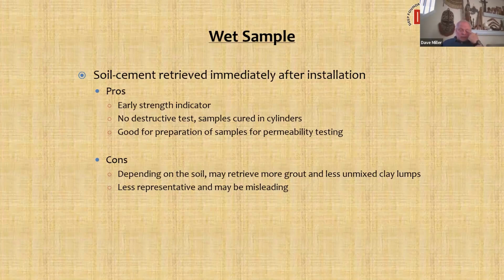So obviously the cons are, depending on the soil, it may retrieve more grout and less unmixed clay lumps. If you have a very cohesive soil and you're getting these lumps, you'll have a tendency for the grout to flow into the sampler easier than the lumps, and that could lead to some results that aren't representative. And that could be misleading.